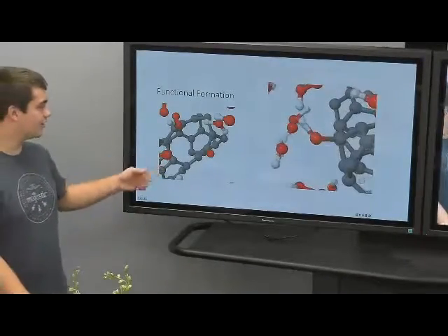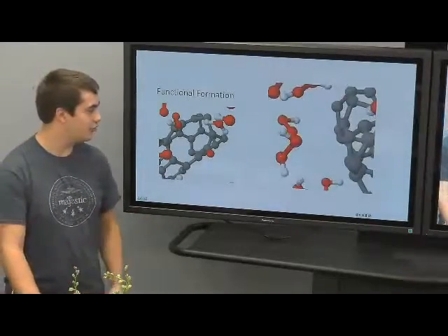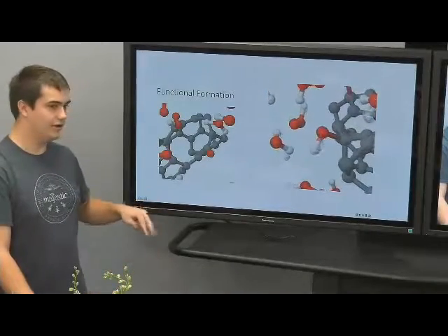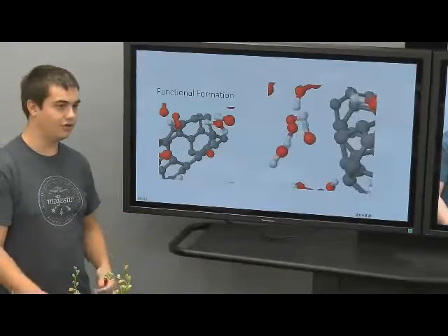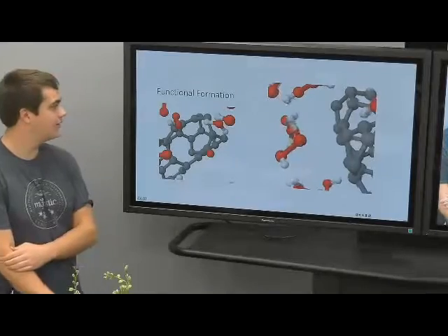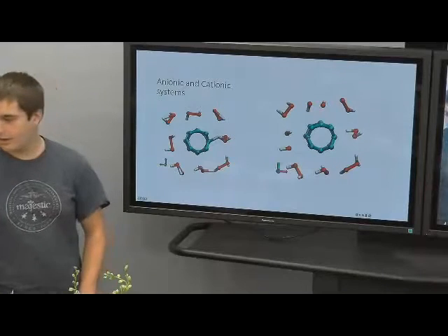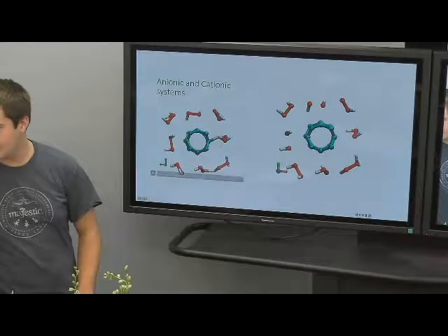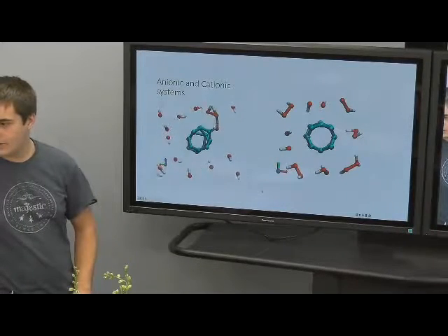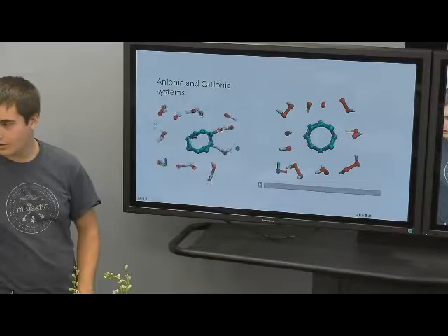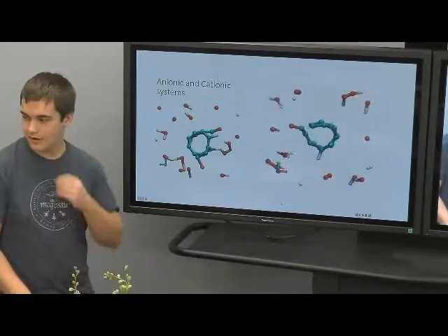And in this still frame here, it's kind of hard to see, but the 6-member ring on the carbon nanotube was functionalized with 3 different oxygens, and it actually broke and created a hole on the nanotube without dissociating a carbon off of the nanotube. I also looked at the system under both cationic and anionic states. The anion is here, and we see more reaction, but nothing like the cationic state where the whole nanotube kind of just breaks apart.